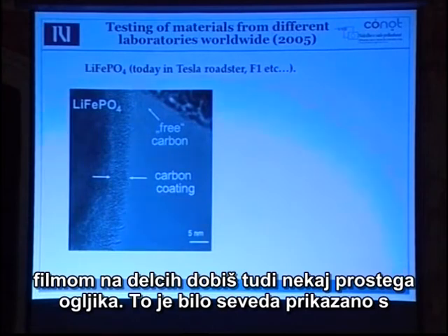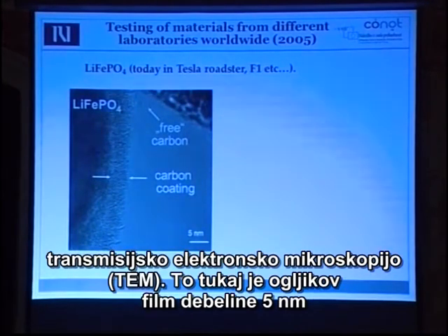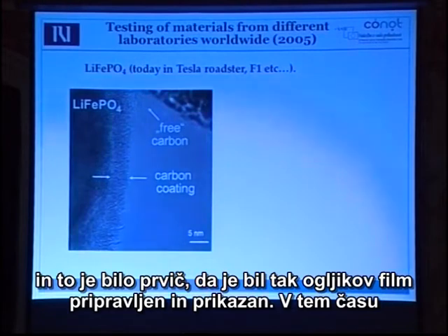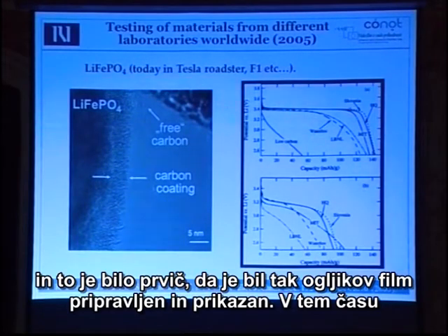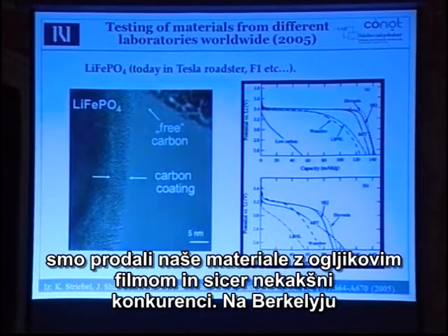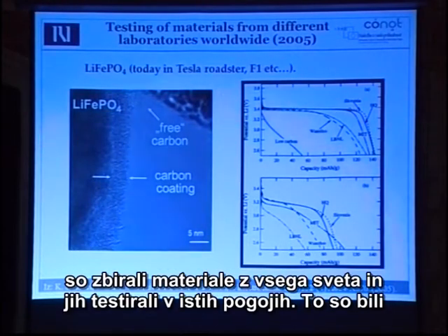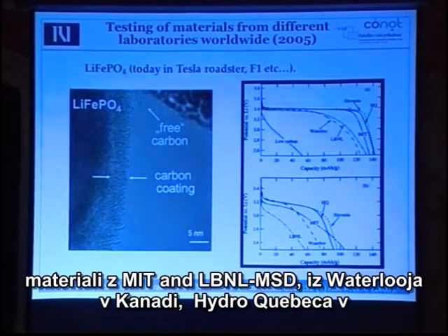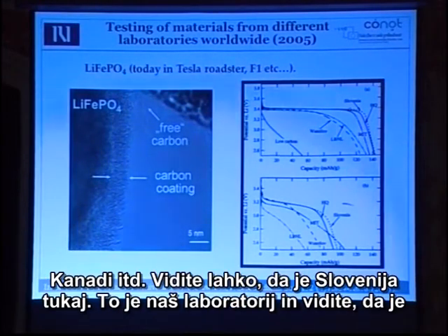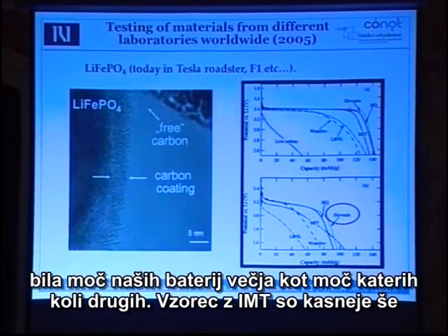This was demonstrated, of course, on the TEM. So this is 5 nanometer carbon coating here. This was the first time ever shown such a carbon coating and prepared. And during that period, we sent out our materials that we had with this carbon coating to sort of competition, so to say. In Berkeley, they were gathering material from everywhere from the world and testing them under the same conditions. So for example, these are materials from Lawrence Berkeley, from MIT, from Hydro-Quebec, from Canada, and so on. And you see that Slovenia is here. This is our lab. And you see that our power of our battery was better than anyone else's.